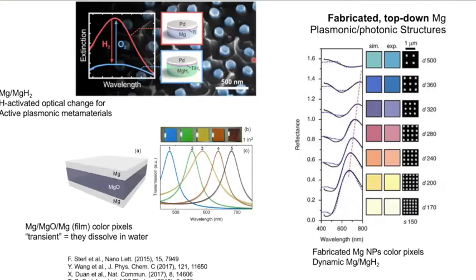We're not the only ones that have been working on magnesium. This is relatively new and growing as a field. But most of the effort until about 2018 has really been in fabricated structures. So here we see, for example, pucks that have been fabricated with hole-mask colloidal lithography. And these pucks were used to move from magnesium to magnesium hydride. What's great here is that magnesium is plasmonic, magnesium hydride is not. So there's a huge shift in the optical spectrum.